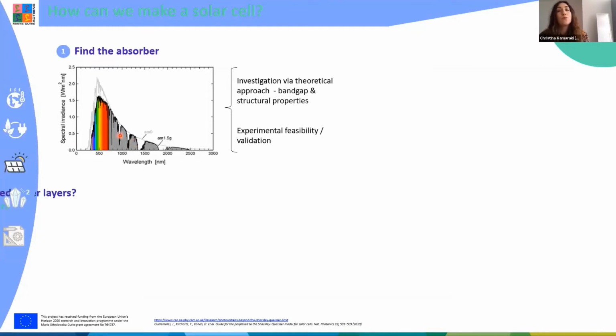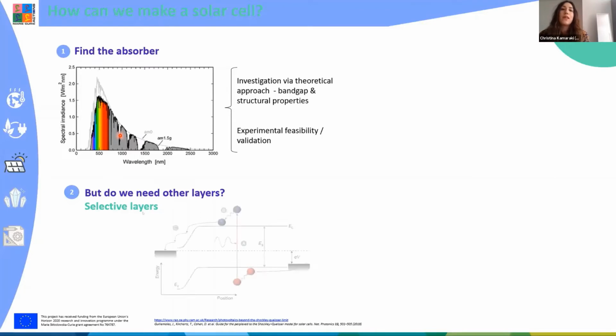Do we need anything else apart from two metal contacts to extract the carriers? So the answer is yes, we need selective layers. So an electron, even if it is excited to the conduction band, usually it prefers to return back to the valence band where the energy states have lower energy. So in order to avoid this relaxation, we need to pull the electron to the contacts, and thus we need a driving force. This driving force is provided by the selective layers.